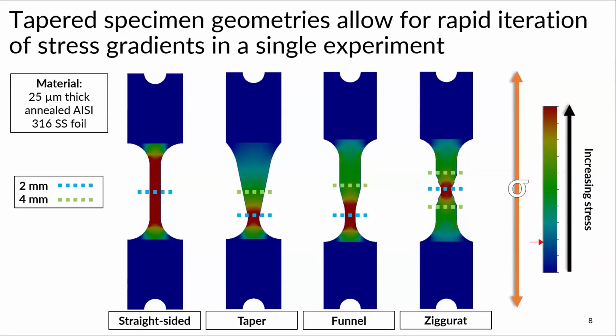And so we tried to pivot into how much more data we can get from 1 sample. Our second iteration was the taper specimen, in which we could achieve 2 millimeter and 4 millimeter in a gradient. And we could achieve a stress of 316 megapascals in the 2 millimeter and 158 megapascals in the 4 millimeter. Then we went on to the funnel, which is a little bit more elongated. And finally, we are on our fourth geometry, the ziggurat, in which the taper is uniform on either side.